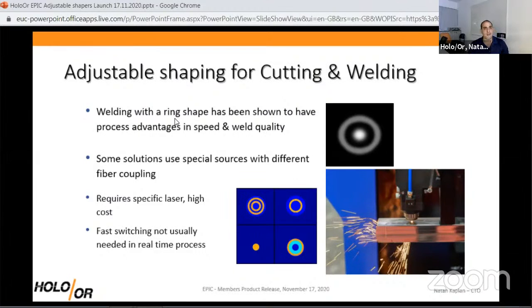Specifically, I've used this example of the ring mode, which has been shown to be very useful for welding and cutting processes. Now there's a lot of buzz around cutting and welding with ring mode lasers. I think there are many of these, for example, from Trumpf, from nLIGHT, and at least two other companies, Coherent, that I know of, that offer fiber lasers for cutting and welding that have both the core mode and extra higher modes with more power. And there are quite a lot of publications showing that this gives you better keyhole stability, less splatter, and generally a better weld quality.